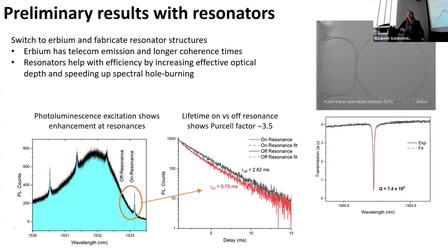How dense are the erbium emitters in this case? So the doping concentration in here, I want to say it's 0.1%. Weirdly, the erbium is actually a substitutional dopant for lithium. Weirdly, because if anyone who's ever looked at a periodic table, erbium and lithium are not the same size, but it's a substitutional dopant for lithium.